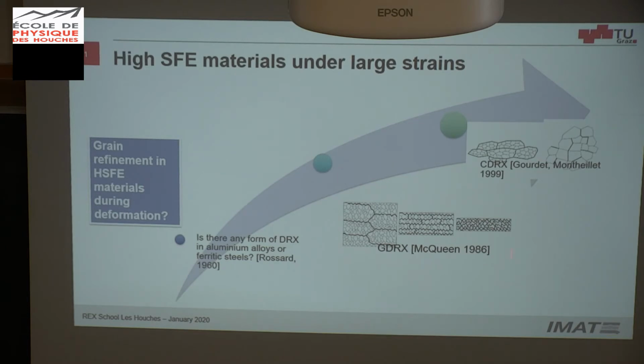Then in 1986, McQueen came with the idea of, yes, there is some type of recrystallization when these high-angle grain boundaries get flattened by the compression, for instance, and they get pinched off by the formation also of subgrains. And with this, I have what is called geometric dynamic recrystallization, which means you need a huge deformation to get very, very thin grains, plate grains, and then also formation of subgrains due to dynamic recovery, and then you have the pinching off of the high-angle grain boundaries and deformation.